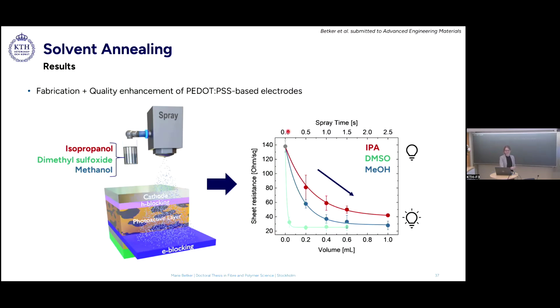And this is one example here just to illustrate the process. So here you see again, we have the resistance. So low values means high conductivity for each of the 3 solvents. And you see with increasing spray volume, the resistance decreases. And we have the least effect for the isopropanol in red and the largest effect for the DMSO here in green. And yeah, I will now explain to you why that is actually.